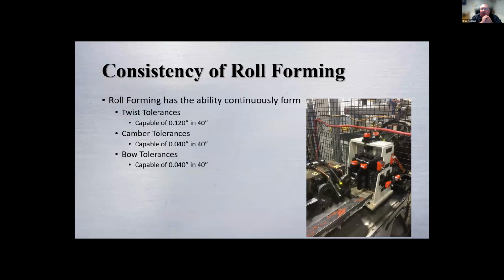Here's our twist. Our twist tolerance is basically 120 thousandths in 40 inches. Another way to say it from the one I was talking about earlier. And like I said, that is take a 40-inch part, you hold it down on 2 points on one end, you look at the other, and the corkscrew effect of it will be within that 120 thousandths of an inch. Can you do better? Yes, it's done better all the time. It really depends on your material, and do you have the machine size right, and is the tooling correct? Camber or sweep or down bow, everybody has different terminology for it, but it's 40 thousandths in 40 inches, and bow is 40 thousandths in 40 inches.